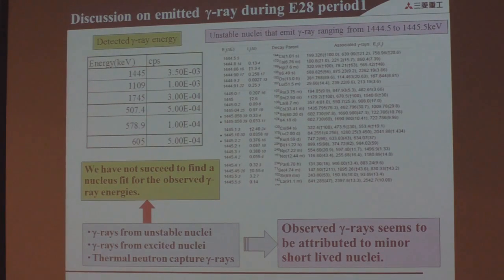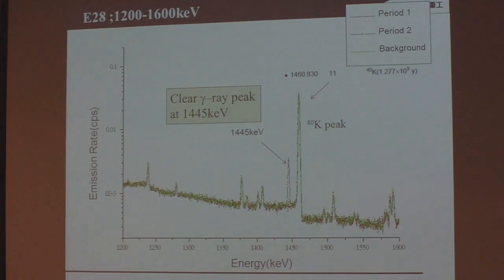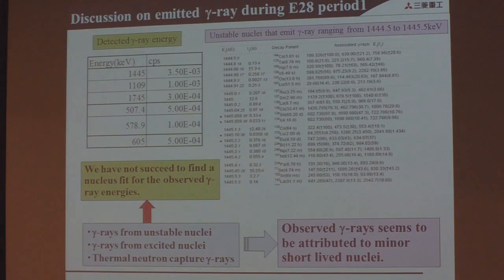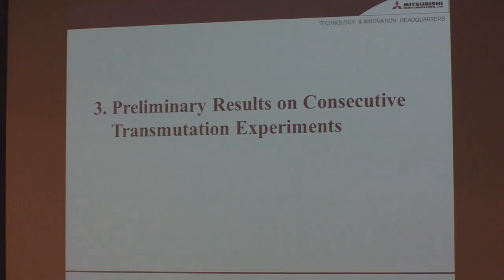Also, this experiment, we tried to replicate it. We tried two times, but we could not detect the same gamma ray. So it's a very difficult experiment. This peak is very clear, but the rate is not so high. So maybe this observed gamma ray seems to be attributed to a minor short-lived nuclei. So I would like to continue this gamma ray detection research.